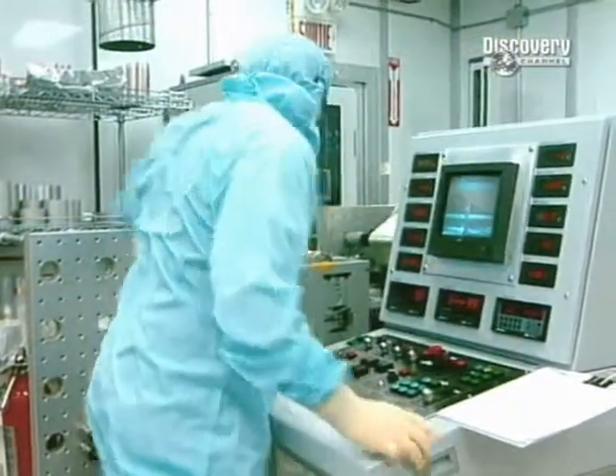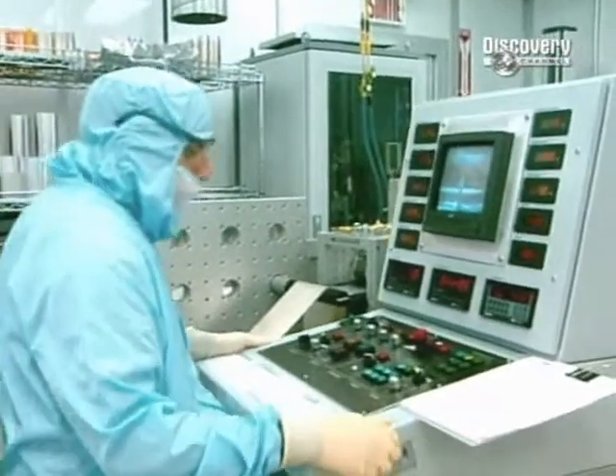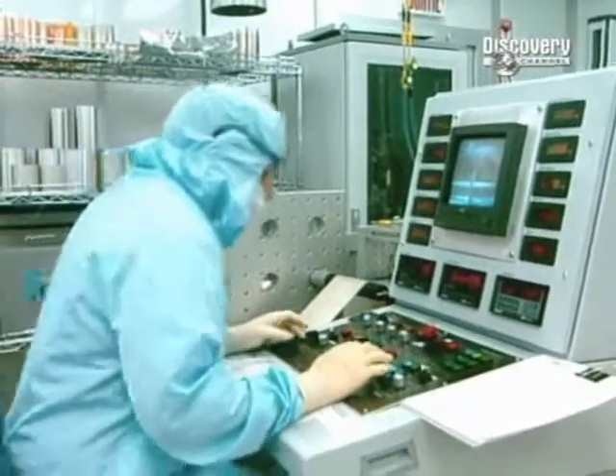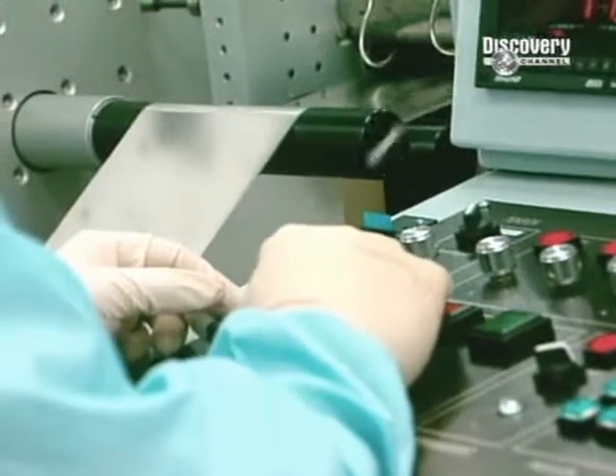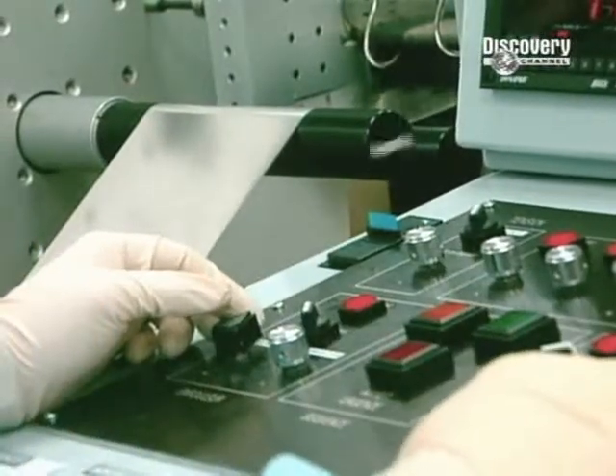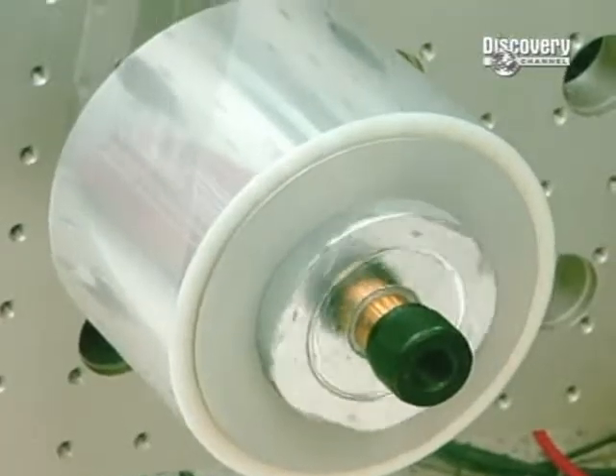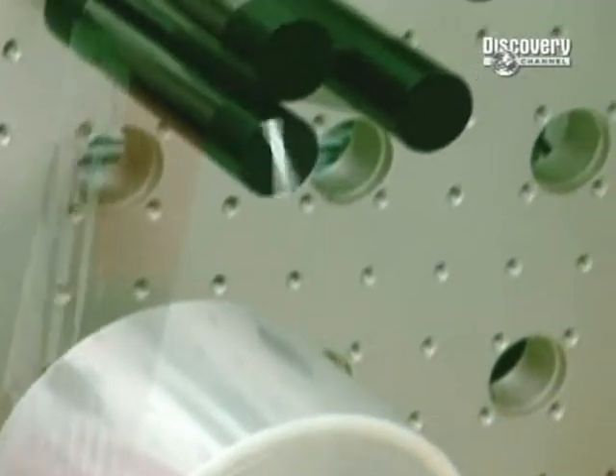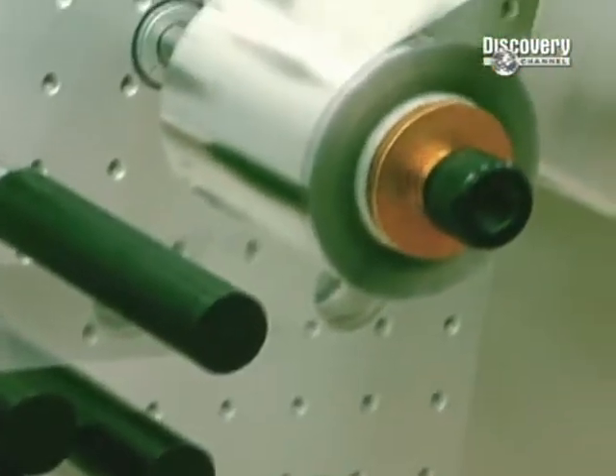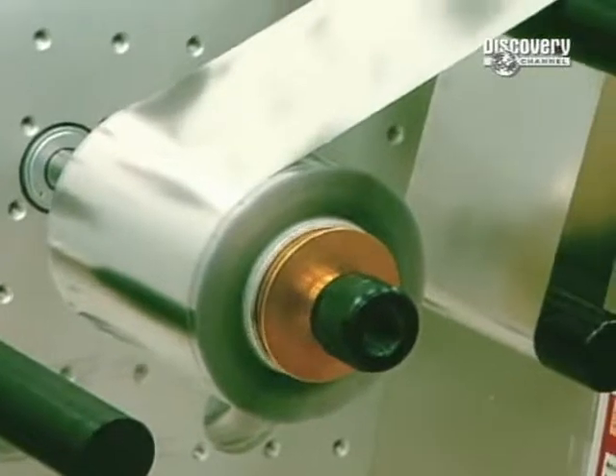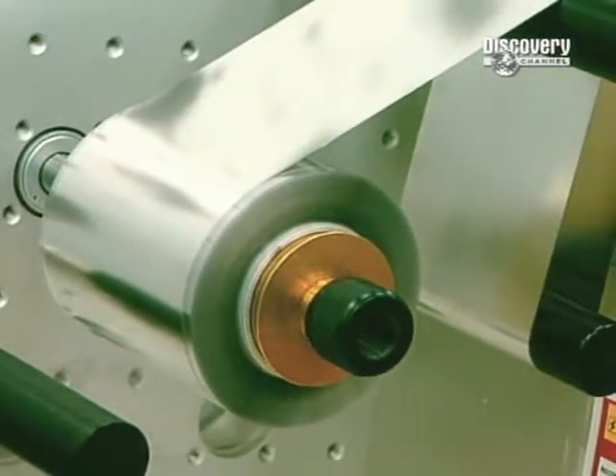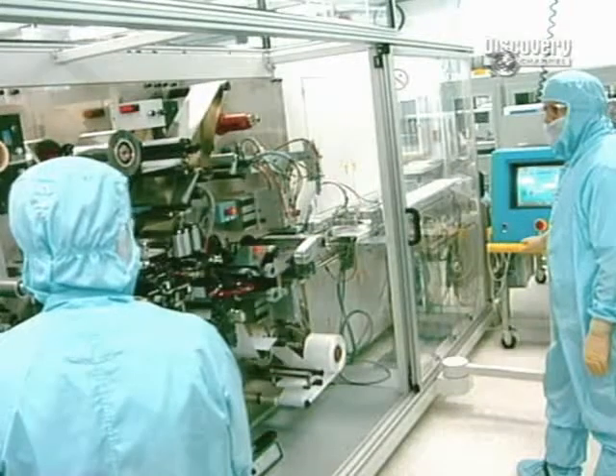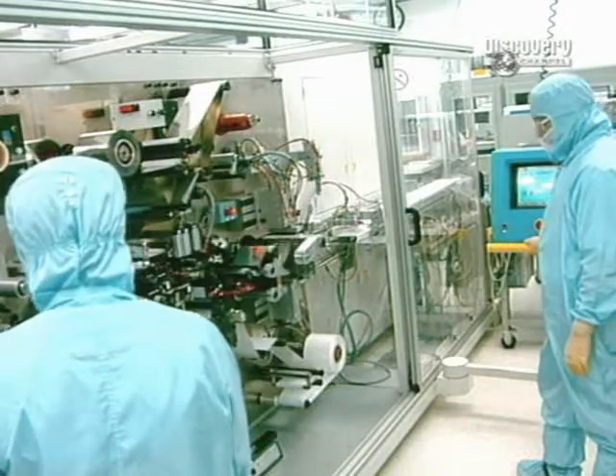This laminator completes the thinning of the sheet to between 20 and 40 microns. The resulting 2-kilometer-long sheet will go into making 210 battery units. Lithium is a soft, sticky metal. For this reason, a polypropylene film has to be fixed onto the lithium sheet. Without this protection, the sheet would adhere to itself and become unusable.